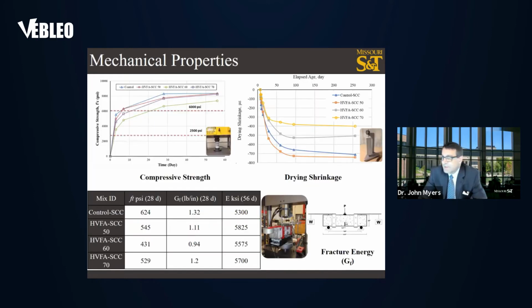In addition to the rheological properties, mechanical properties were also measured following mostly ASTM procedures when applicable. We measured compressive strength, as you can see in the upper left-hand corner, with our 3-day targeted strength requirement, all satisfied that, as well as our 28-day strength requirement. And all of our mixes easily satisfied those target strength requirements.